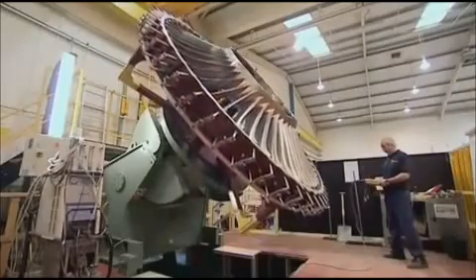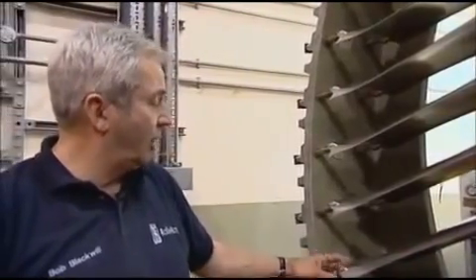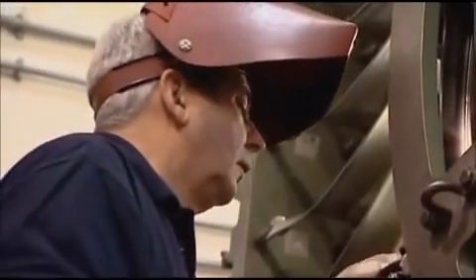One of the most experienced is welder Bob Blackwill. His job is to fix in place a ring of titanium blades that'll channel air smoothly into the engine — a highly specialised form of welding. I'm a TIG welder and carbon sheet metal worker; I've been doing this job for 22 years. All these vanes are different — different cambers to achieve the best airflow. Every weld on this job will be x-rayed, so any defects have to be taken out and repaired. When this weld's finished, this vane should leave a tolerance of no more than 5mm radially and 1mm forward and rearward on the blade. It's not machine — it's hand skill, and we think that's a fine tolerance to achieve on a hand weld.